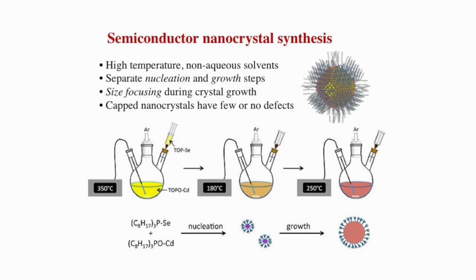Whereas in the case of my colleagues in chemistry, what they do is they use a container like this, and then they put one material, which in this case is cadmium, and then introduce small amounts of selenium here. So by controlling the temperature of this beaker, they end up changing the size of these nanoparticles and control it precisely. So this is the so-called bottom-up approach.